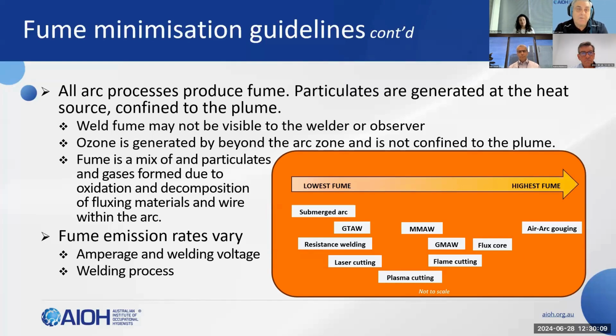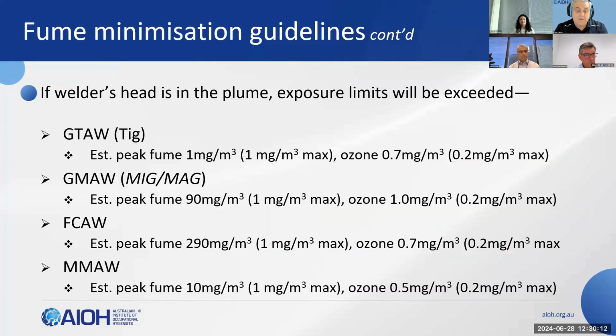Now, if we look on the next slide, you can see worst case scenarios as far as fume and emission rates that were measured in still air during the development of Weld Australia's guidelines. Interestingly, the work demonstrated that most, if not all, open arc processes required a measure of fume control primarily to manage the ozone generated when these numbers were first generated. Now, from the fume particulate perspective in still air, the fume levels generated will be high in many cases. But as I've stated previously, the fume may not be readily available or visible to the welder, and I should add, it may not be visible to the observer either.